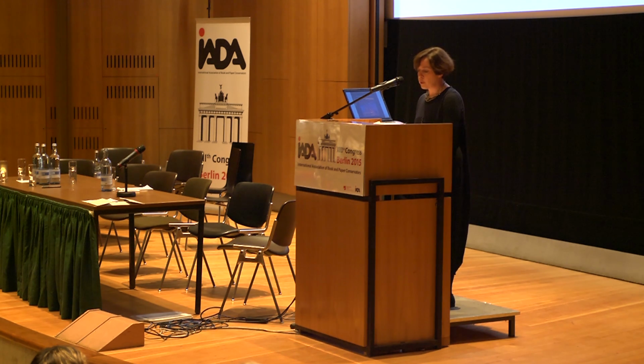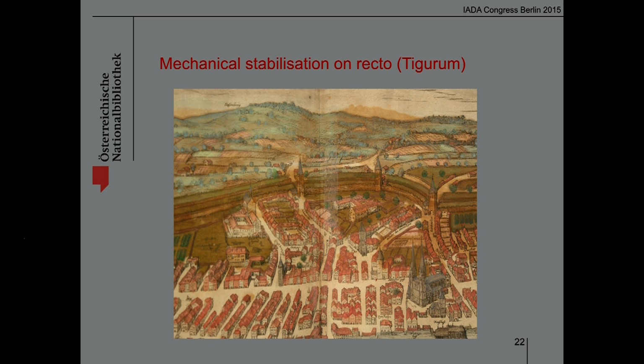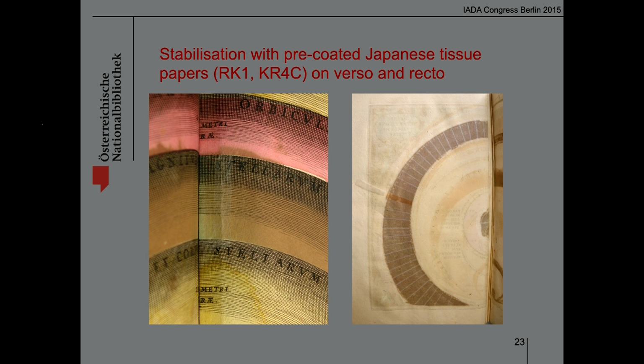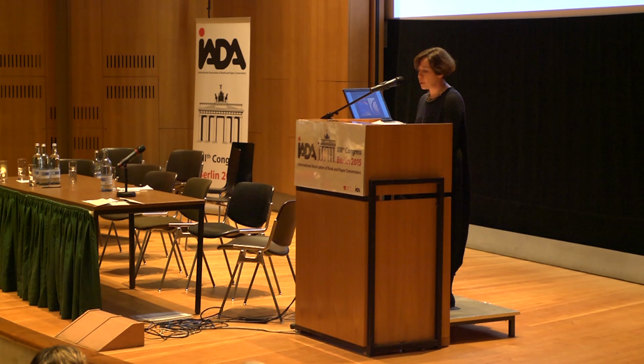On the recto of verdigris, RK1 or KR4C were applied in cases where a tear had to be secured from both sides. KR4C, a cream-colored 4-gram paper, was applied on very dark areas because it is less jarring than a white paper. For the stabilization of large areas, like on maps in Harmonia Macrocosmica, the pre-coated Japanese papers were applied in small pieces following the form of a large colored area.